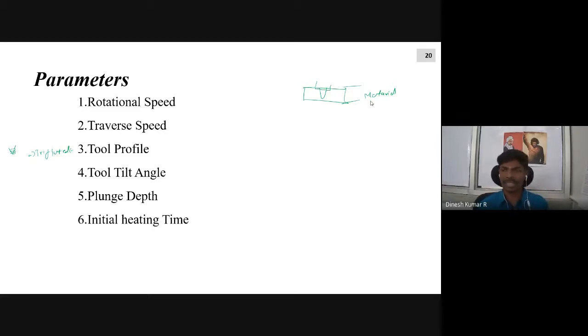Then initial heating time. What is this initial heating time, sir? You are going to plasticize the material and fuse it. You are not going to completely melt it, you are just going to plasticize the material. You introduce a tool, and heat is generated by the frictional force, and that frictional force creates semi-solid metal layers through the process. The time required for creating those semi-solid metal layers is what is called the initial heating time. With that, we have a clear understanding of what it is and how much is required, and this can also give you a better result.